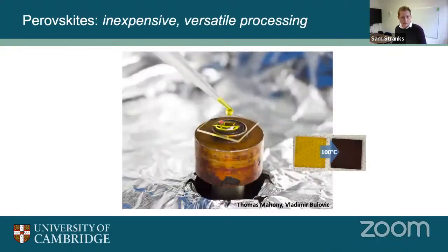So when we process these materials, what we do is that we typically have inks of these. We dissolve the salts, the precursor salts that make up these ionic materials. And so in the center here, I've got an image of this ink being dropped down onto a glass substrate, and then we spin coat them in the lab at a few thousand RPM, and this forms a really nice and uniform film. You can see in this yellow image on the left here. And then we heat them gently.